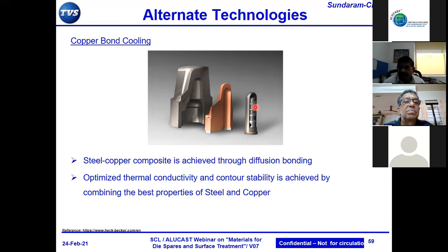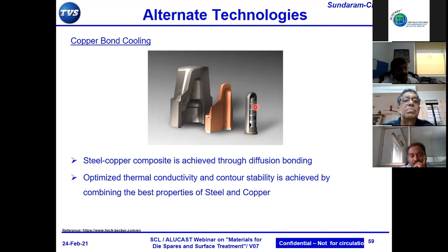The second thing is we need to have a lot of internal cooling rather than spray cooling. We should use spray basically only for lubrication and the non-sticking requirement of the part to the die. So if we use the spray and not excess spray for cooling the die, and have a lot of internal cooling, that really helps in extending the life.